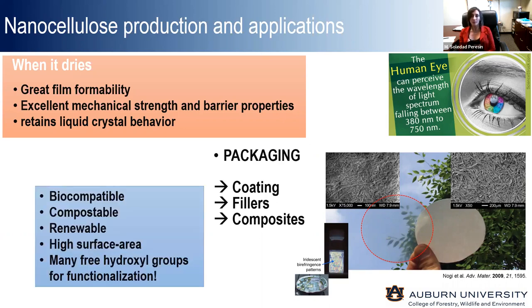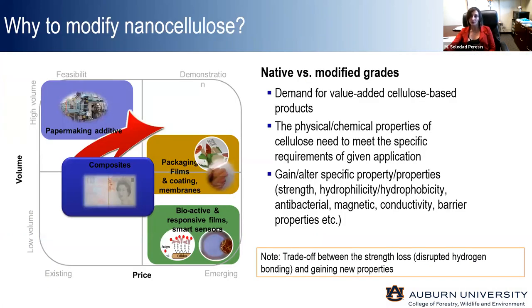And because it's made out of biomass and renewable sources, it's at least compostable, if not biodegradable in some cases, and it's going to be biocompatible. And it has a much larger surface area than the microscopic fibers as such, which gives us a larger amount of hydroxyl groups that we can play with for functionalization. And this is very relevant because we can take this template and apply all the chemistry that we know works with hydroxyl group chemistry, and then impart new functionalities in this great substrate that will further increase the applications and the markets, if you wish.